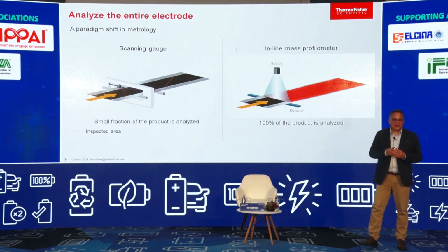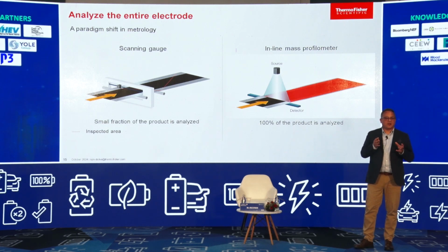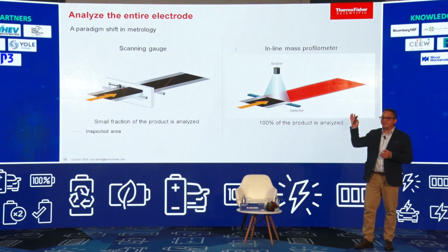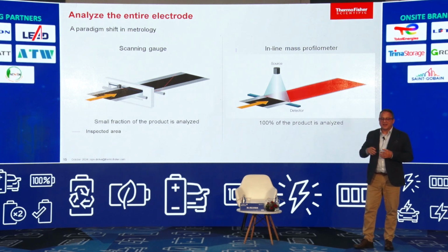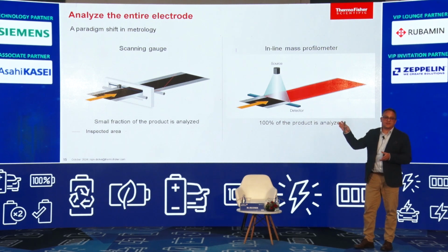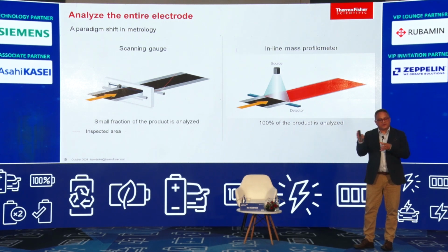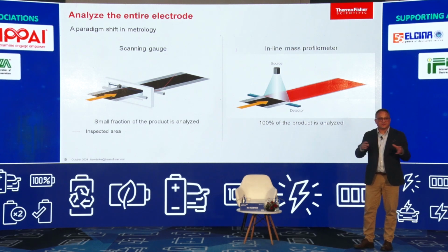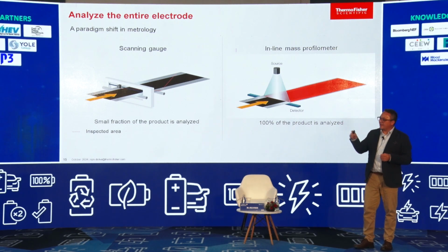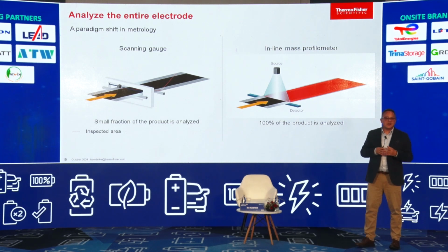So if you take a look on the picture on the left-hand side of the screen, it shows a conventional scanning gauge. Many companies are exhibiting these gauges this week at the battery show. This is how batteries have been produced for the last 20 years. You simply measure the thickness of the material by moving the sensor back and forth across the coated material in a single zigzag line. The challenge here is the line covers around 2% of the material. 98% of the material goes uninspected. You have no idea if there's a thick patch, a thin patch, a defect.